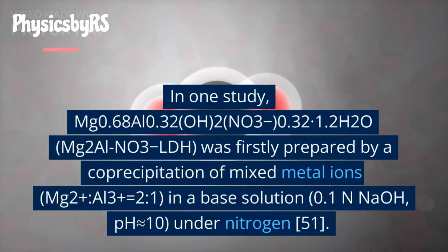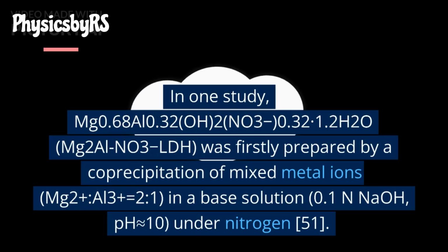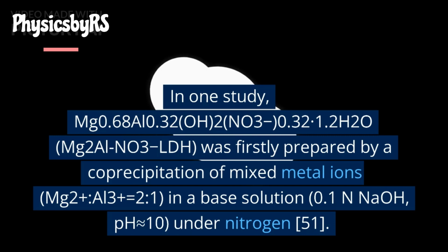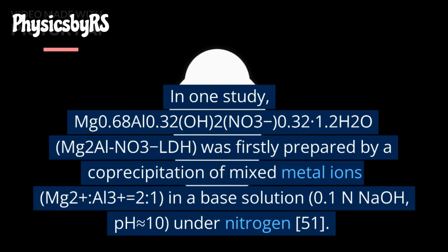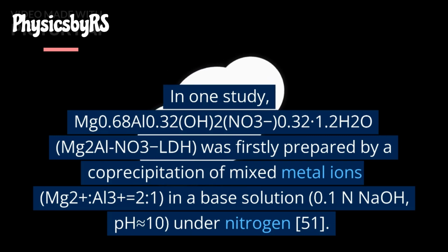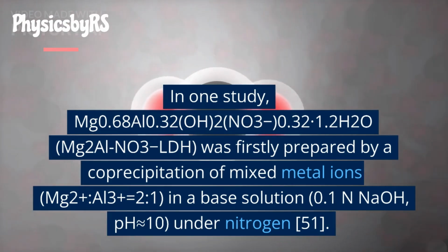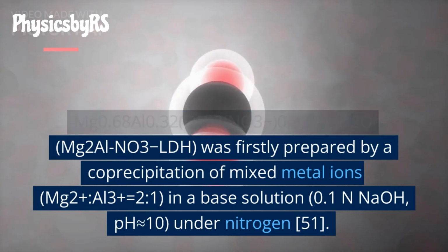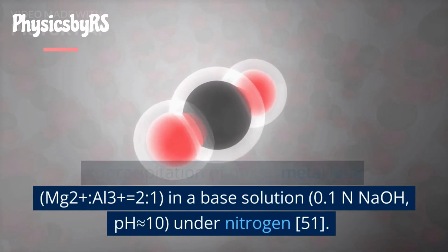In one study, Mg0.68Al0.32(OH)2(NO3)0.32·1.2H2O, Mg2Al-NO3 LDH, was firstly prepared by a coprecipitation of mixed metal ions, Mg2+:Al3+ equals 2:1, in a base solution, 0.1 N NaOH, pH approximately equals 10, under nitrogen.